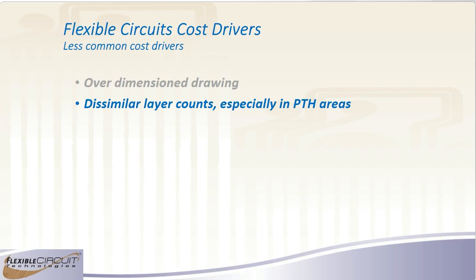Dissimilar layer counts. What you want is, in any area that has a plated through hole structure, you're going to want to make sure that the layer count is the same in each of those areas. I've had applications where I've gotten designs in where a circuit looks kind of like a dog bone, and on one end it's 6 layers of circuitry, and on another end it's 4 layers, and they're asking to remove the 2 layers thinking it's going to save money. And it's like, well, it'll definitely have an impact on the cost, but not the direction you want it to go. If you ever have that situation, you either need to figure a way to get the 6-layer down to 4 layers, or add 2 pad layers on the 4-layer to get up to 6 layers, because you want to have the same layer count in all areas that have plated through holes.